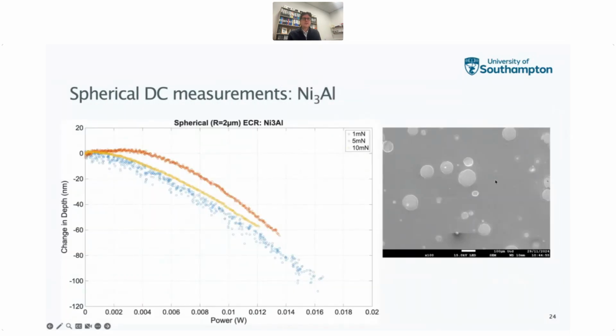If you then try and do it on something that has a slightly higher resistivity, like the intermetallic phase, it then starts to become a bit interesting. So if you put a 5 or 10 millinewton load with this spherical 2 micron radius indenter tip on one of these particles, you do get this thermal expansion effect that we've been observing. But then if you put quite a light load on, where you're not penetrating the surface too much, you also see the tip being pushed out, but it's a lot more stochastic in its response. You see it's a lot more bumpy on this curve.